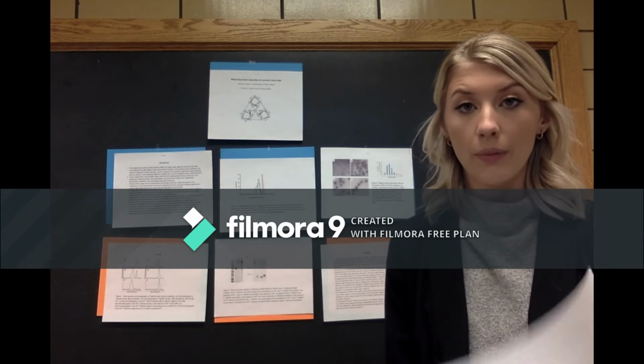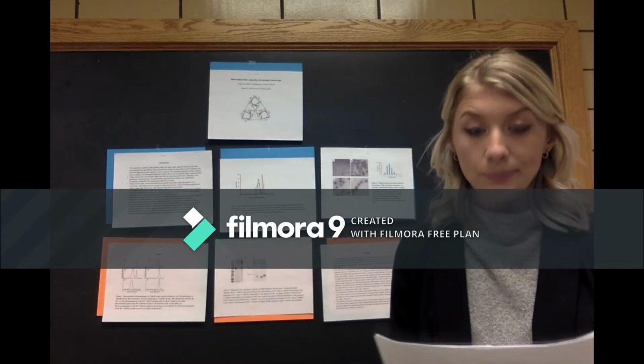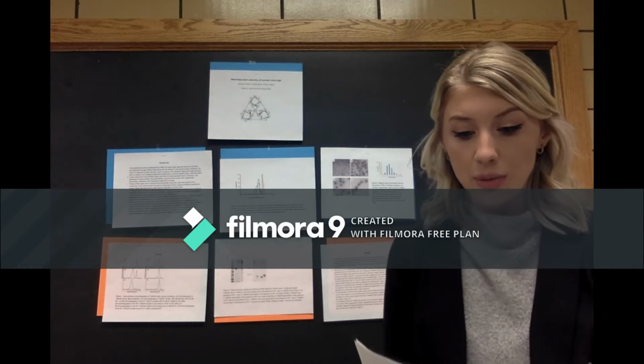A metal-dependent coiled coil design that was previously shown to assemble into a homotrimeric parallel coiled coil in the presence of divalent transition metals was used. They genetically fused it to a trimeric protein to facilitate the metal-dependent assembly of this protein into a tetrahedral structure. In the presence of divalent metal ions, this construct assembled into discrete higher molecular weight particles consistent with the formation of a tetrahedral protein cage. Protein assembly was found to be reversed either by the addition of metal chelators or by decreasing pH.